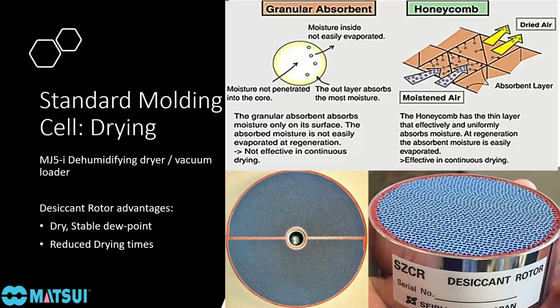Also, during regeneration, our flat desiccant surface allows us to regenerate the desiccant quicker using less energy. Imagine if you were going to dry a t-shirt out in the summertime. You would spread out that t-shirt and put it on a clothesline because it would dry out much faster than if you crumpled that t-shirt into a ball and left it on the ground. So that's the same concept that we use with our flat desiccant surface.